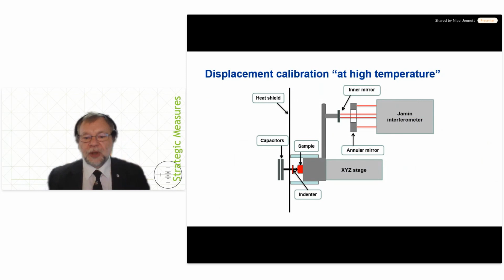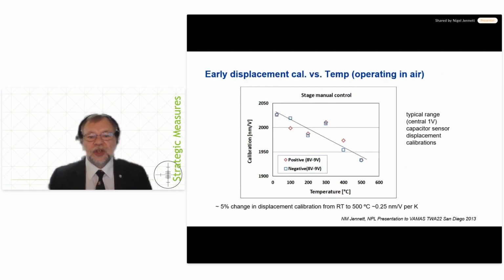Great. So you think, well, it's all at room temperature, so why is there a problem? Of course, it's always best to try. And what we found was that as you change the temperature of the hot zone, we got around about a 5% change in the displacement calibration. This is not thermal drift, this is an actual calibration change. So a nanometer is no longer a nanometer at 500 degrees Celsius. And that's a problem, because the limits on displacement and force calibrations in the standard are about 1%, that sort of order typically. So now we're talking about having to calibrate your system as a function of temperature.